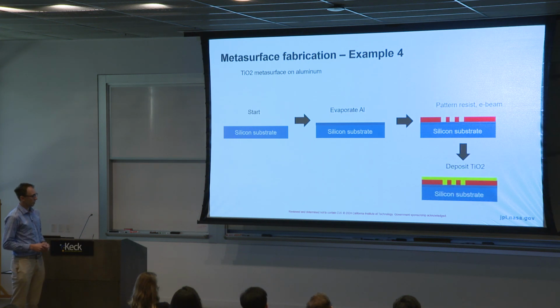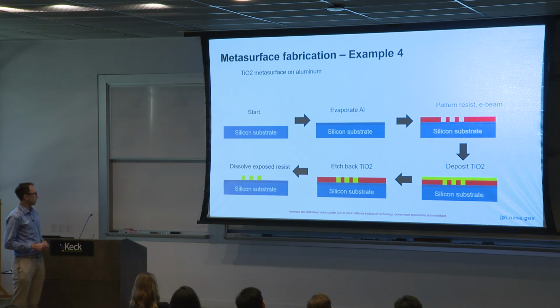And then you deposit titanium dioxide. And in this particular case, you need to make sure to choose a deposition method that's compatible with the feature sizes that you want. So if they're very, very small, you need to choose a very conformal method to kind of completely fill in these structures. Then you would etch the titanium dioxide back to expose the photoresist, which you then dissolve in a solvent in the end.